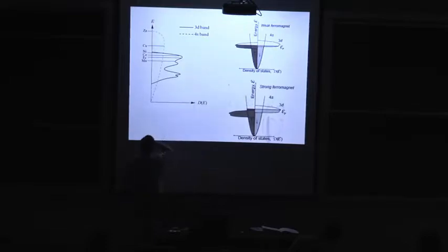This is a tight binding rough diagram, a cartoonish representation of a band structure, now represented in a more realistic fashion. This curvy band structure. Copper, the Fermi level is above the 3d band, it lies in the 4s band. Zinc is right at the top because everything is completely filled. The 4s and the 3d are completely filled for zinc. So then you have nickel, cobalt, iron, manganese. Okay?